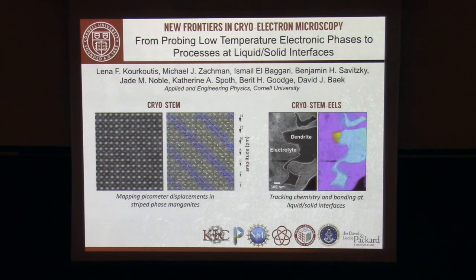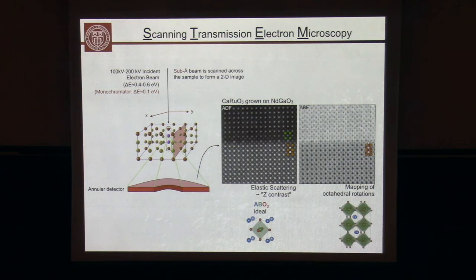My first introduction is usually that electron microscopy is very powerful. Most of you might know how it works. For those of you who don't, this is typically how we operate it. We focus a very high energy electron beam down to subatomic length scales on the sample. So we converge down on the sample, and that electron will interact with the atoms and electrons in the material. We have elastic scattering to a certain angular distribution, and we can collect those elastically scattered electrons. And what does that give us? It gives an elastic signal of the structure. And so for a long time, electron microscopy has produced images that let you look at the atomic structure and quality of hetero interfaces, here for example between two complex oxides. And you see, for example, here this reconstruction at the interface.